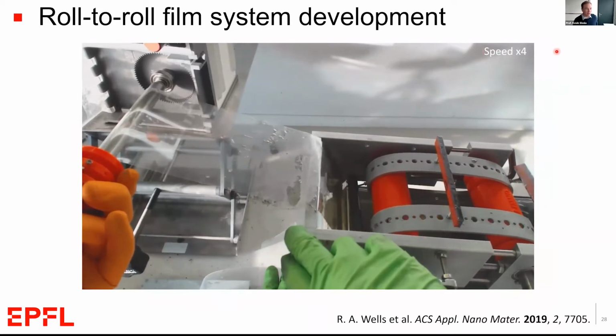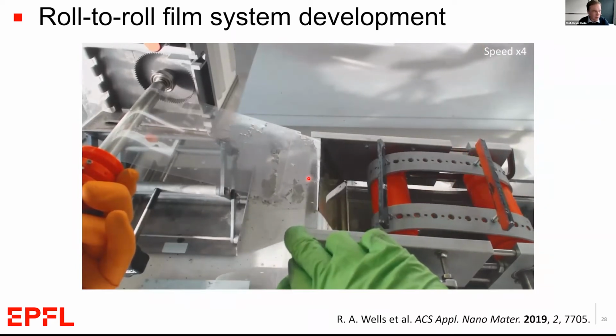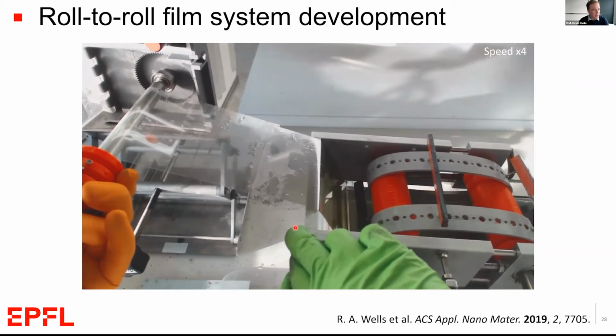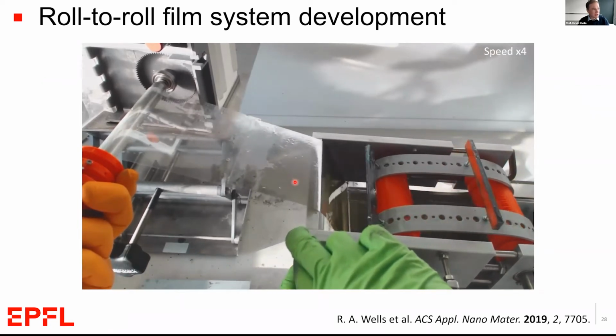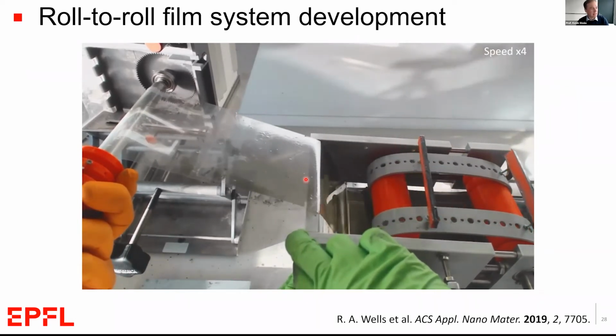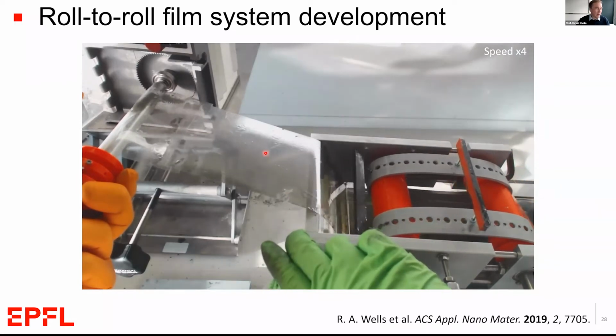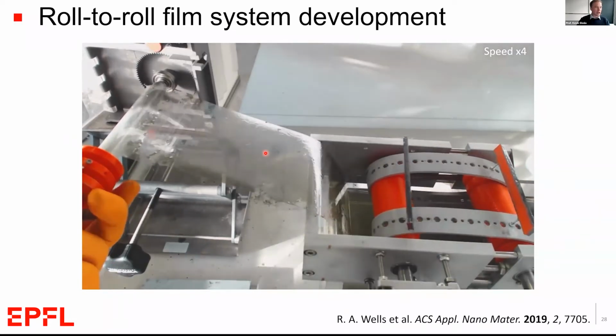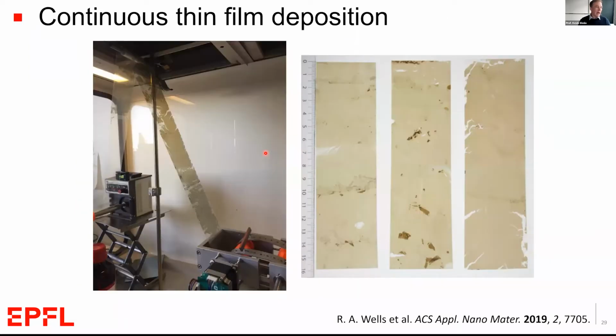This is sped up about 4 times. We can see these paddles pushing that self-assembled film. Our plastic substrate is fed through, and it picks up the nanoparticle film, all in good alignment with the substrate. Now, this could be improved. Of course, the films that we make aren't perfect, but it's a good start to demonstrate that, at least in concept, this type of deposition could be scalable in a roll-to-roll sense.